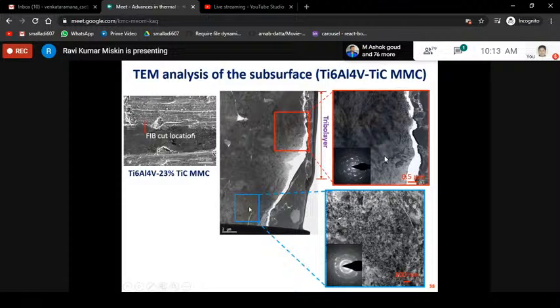So why did we cut it this way? Because in a single cut, we wanted to see how the microstructure is below the tribolayer and also away from the tribolayer. So on the middle image, you can see the cut, and then we rotated it and saw it in the microscope. There you can see below the tribolayer, your grains are a bit larger. So technically, if your grains are larger, you have less deformation. In the blue image, where the mouse is pointed, that is under the wear track, which is not covered with tribolayer. There you have highly refined grains.